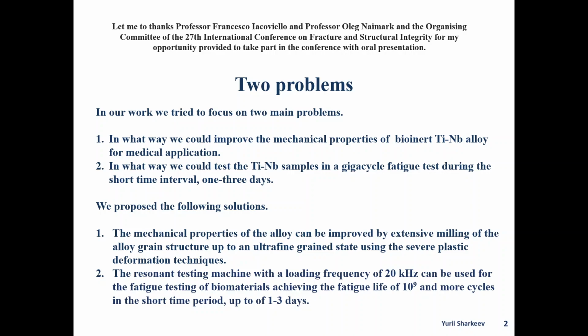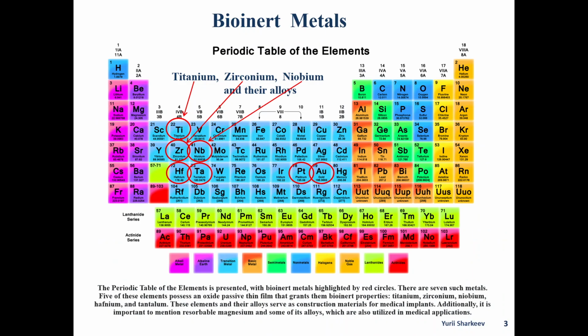The mechanical properties of the alloy can be improved by extensive milling of the alloy grain structure up to an ultrafine grain state using severe plastic deformation techniques. The resonant testing machine with loading frequency of 20 kHz can be used for the fatigue testing of biomaterials, achieving the fatigue life of 10 to the power 9 and more cycles in a short time period, up to 1 to 3 days. The periodic table of elements is presented here, with bioinert metals highlighted by red circles.